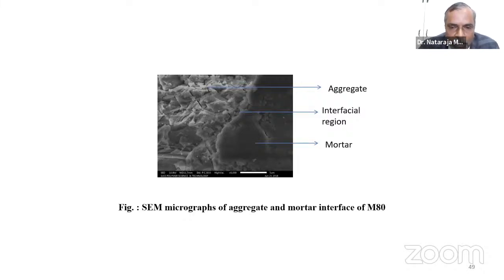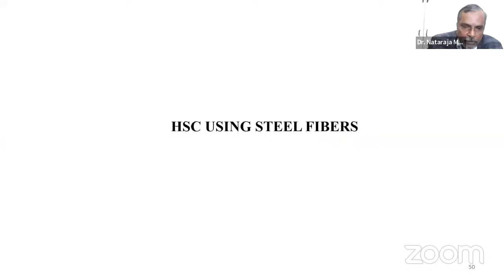This only indicates that the transition zone, which I was referring to in the high strength concrete, is really becoming better, and thereby the bond characteristics of the concrete, especially between the aggregate and the cementitious system, are many times better. And that is where the improvement in the strength properties and the improvement in the performance characteristics of the concrete come into the picture.